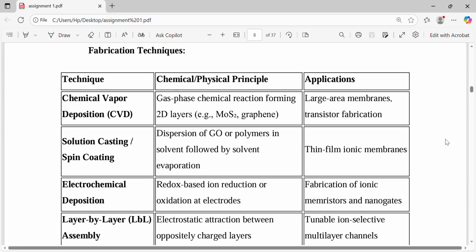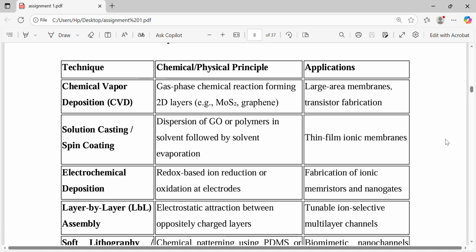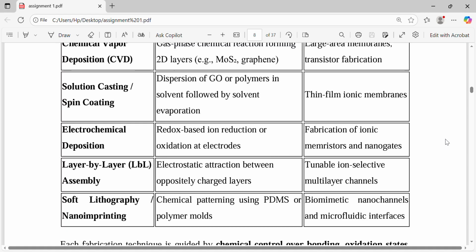Next, fabrication techniques. Chemical vapor deposition: gas-phase chemical reaction forming 2D layers such as MoS2 and graphene. Large-area membranes and transistor fabrication. Solution casting and spin coating: dispersion of GO or polymers in solvent, formed by solvent evaporation, making thin-film ionic membranes. Electrochemical deposition: redox-based ion reduction or oxidation at electrodes, for fabrication of ionic memristors and nanogates. Electrostatic attraction between oppositely charged layers forms tunable ion selective multilayer channels.